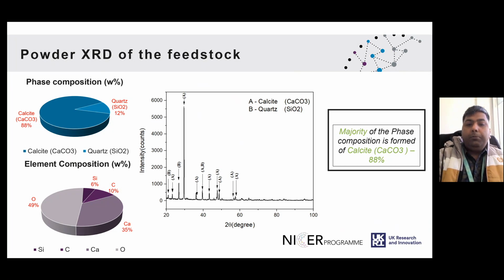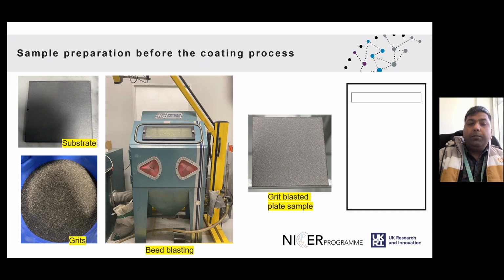Now, when we talk about thermal spray, what we intend to do is obviously, first of all, grit blast the substrate so that any oxides can be removed from the substrate. An artificial periodic surface roughness may be introduced in this process because this allows and enables improved mechanical interlocking of the coating to the substrate. So what is shown here is the grits that are used for doing blasting. And this is the raw substrate.